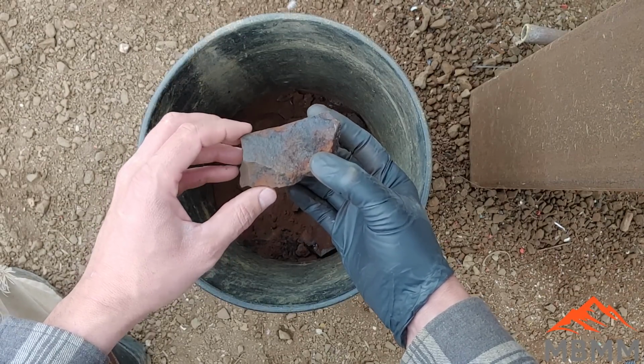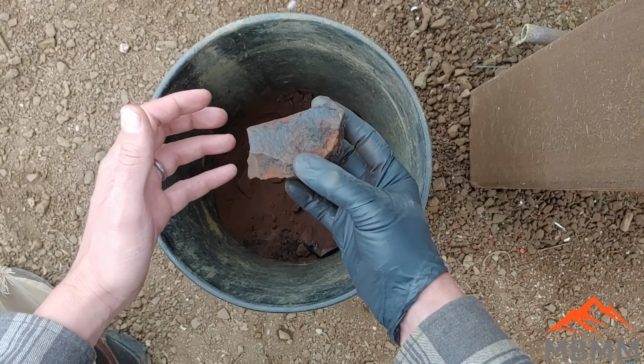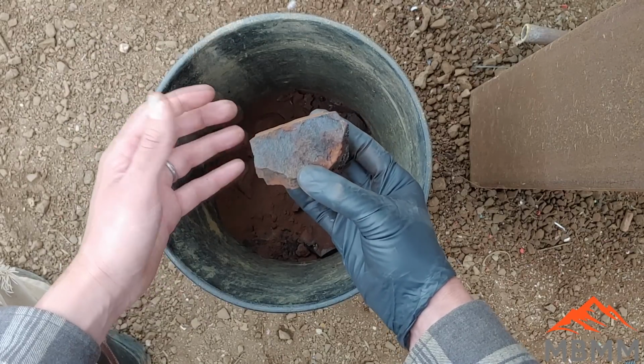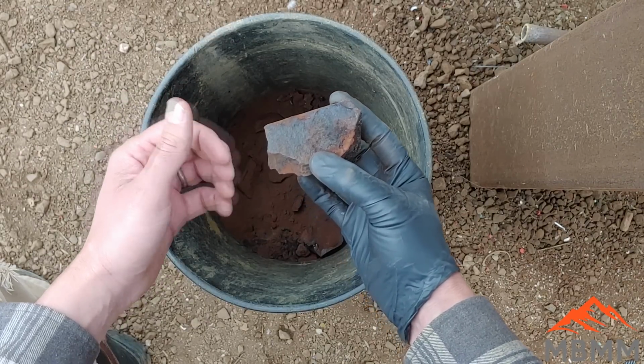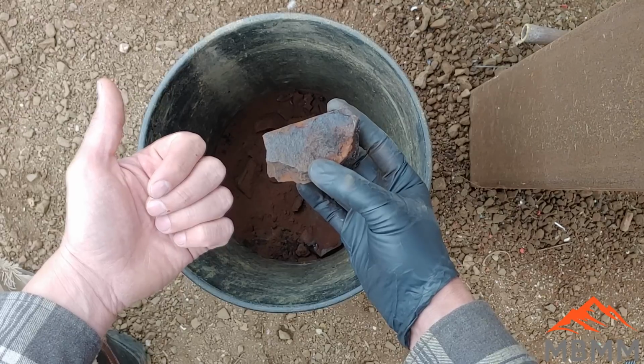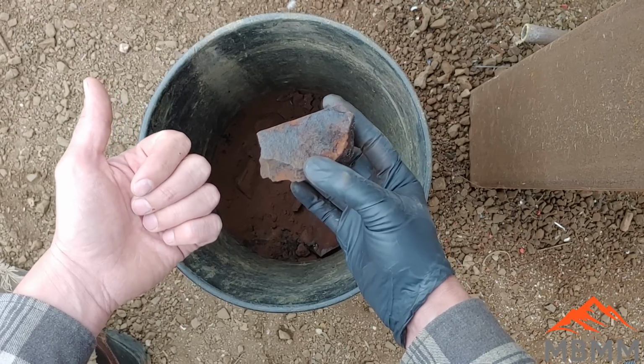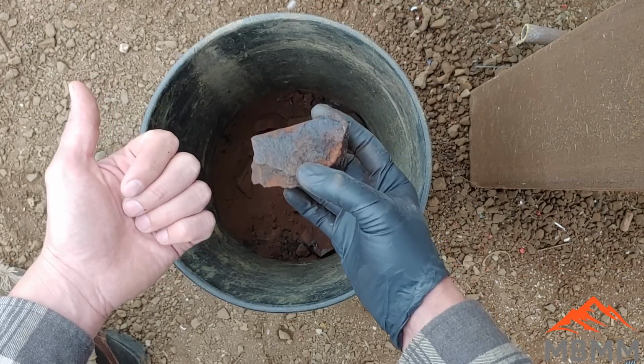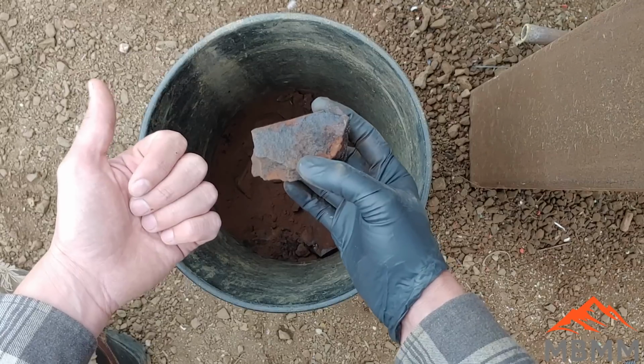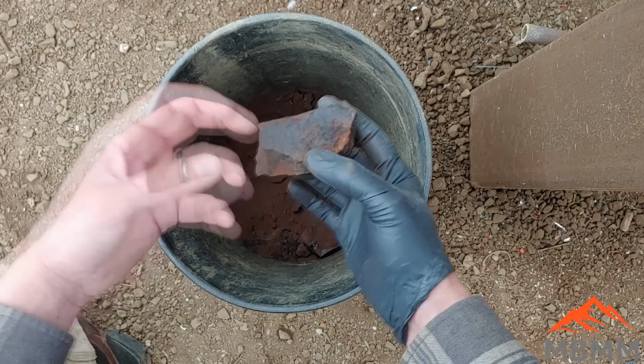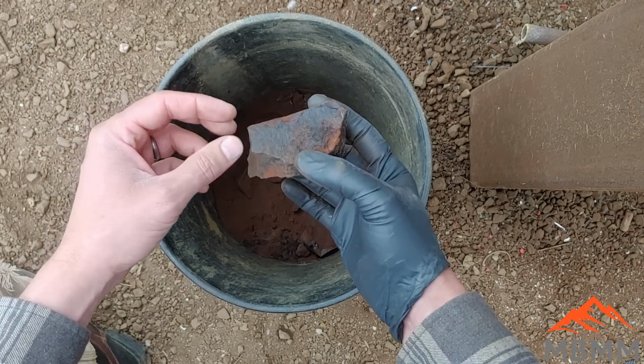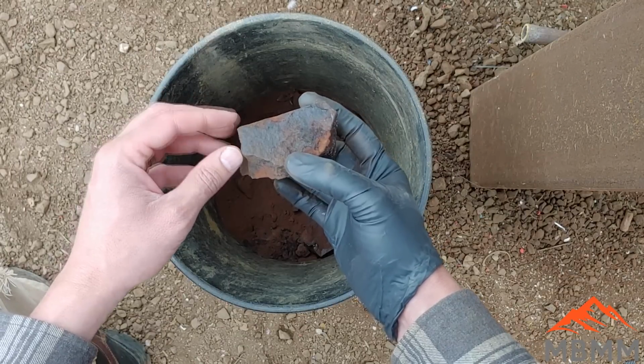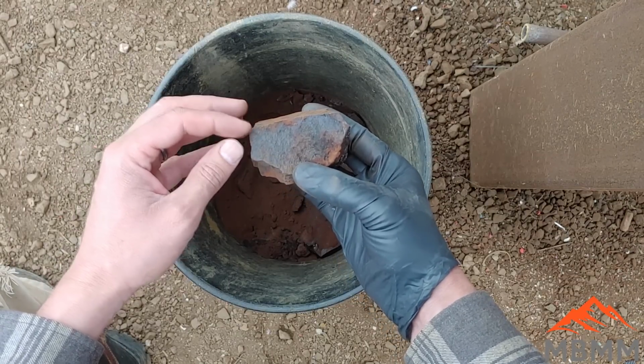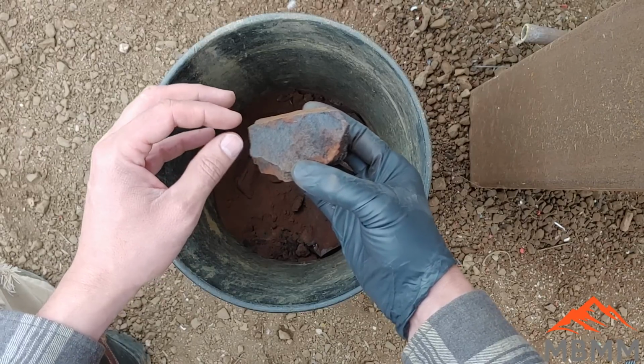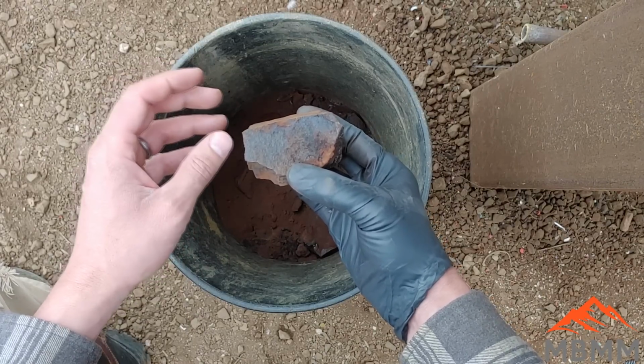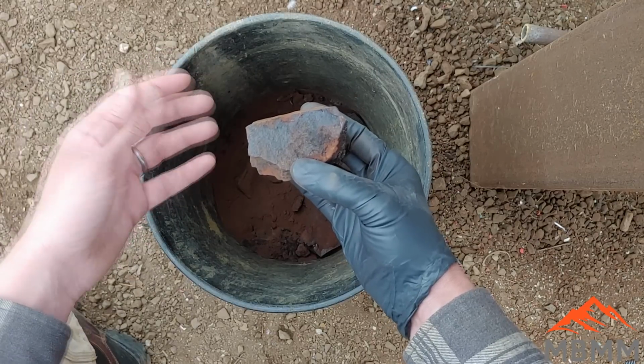There are a couple of common ways of getting rid of the matte or the sulfides in your ore. One is to oxidize them by roasting in the open atmosphere. You heat them up to about 1,000 to 1,200 degrees Fahrenheit, and the oxygen in the atmosphere oxidizes and replaces the sulfur atoms on the molecule with the base metal and converts the metallic sulfides into metallic oxides, and then they can be absorbed into our slag.